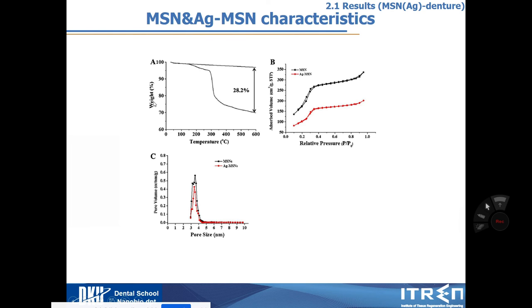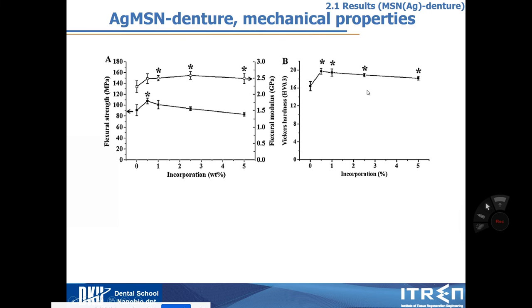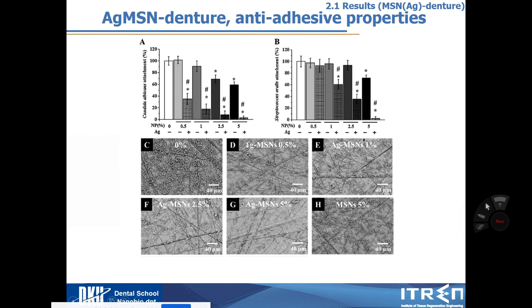I check the silver amount, like 30%, I incorporate in our nanoparticle, and check the nanoparticle properties. Denture is very important to maintain its mechanical properties. From the fracture strength and Vickers hardness, I can choose maybe 5% as the maximum to incorporate our nanoparticle in denture. And then I check Candida albicans, which is a major player to induce Candida albicans disease from the denture.